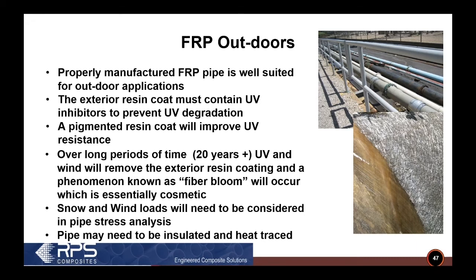And you can see it looks like that chop strand mat, and that's actually something called fiber bloom, where the resin has been taken away from the UV in the wind and the glass fibers are exposed. So that will happen if you don't use a UV inhibitor. If you use a UV inhibitor, you won't get that phenomenon for many decades. And it's really just a cosmetic phenomenon anyway. You could coat over top of that with an epoxy resin or something. But like I say, you're not going to see that for decades if you use a UV inhibitor.